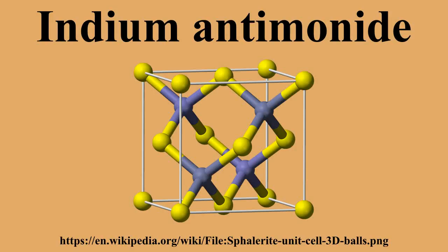Bipolar transistors operating at frequencies up to 85 GHz were constructed from indium antimonide in the late 1990s. Field effect transistors operating at over 200 GHz have been reported more recently. Some models suggest that terahertz frequencies are achievable with this material. Indium antimonide semiconductor devices are also capable of operating with voltages under 0.5 volts, reducing the power requirements.